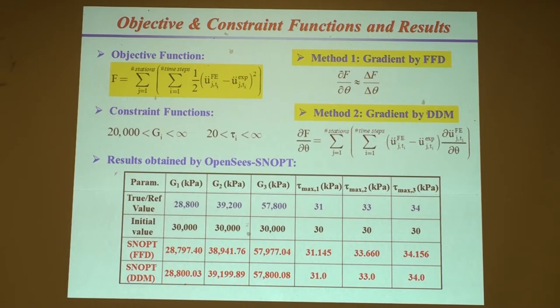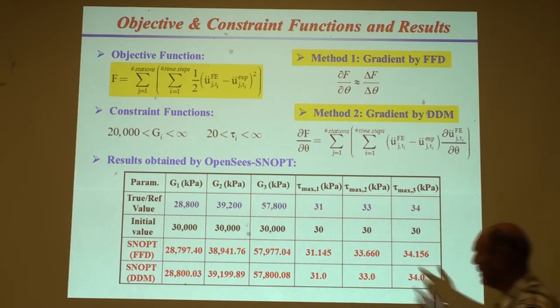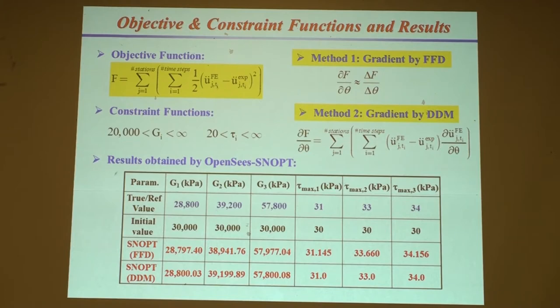So now you see the results. We have three layers, initial shear modulus, shear strength. This is the truth, the reference value, or if you want, the true values. We started away from them. Reasonably, like a good engineer would have some reasonable initial values here. And then if you use finite difference, you would converge to these updated values and DDM to these. So both of them are very close to the true values. The DDM are closer.